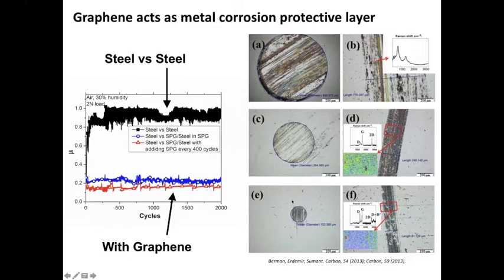If we look at the graphene coated surfaces, you can visually really not distinguish which one is graphene coated and which one is not. But because of these thin layers of graphene, which are allowed to rearrange, along the wear track they start to shear and to reconstruct the whole wear track surface and get this more elongated protection. So with such mobility, with such overlapping, we actually get this improvement in the protection due to the rearrangement of the graphene flakes, thus providing more extended wear resistance of the systems, because even if they start to be pushed to the sides of the wear track, they still allow it to reconstruct.